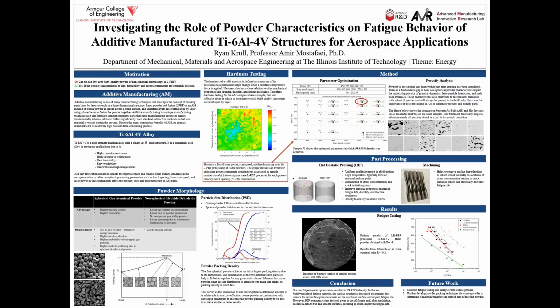To conclude this presentation, successful parameter optimization resulted in 99.935% density. In as-built plus machined fatigue samples, the surface roughness decreased, but there is still a chance for subsurface pores to remain on the machined surface and impact fatigue life. However, HIP treatment closes these isolated pores in the AM parts, and after machining results in a defect-free and smooth surface, resulting in a much improved fatigue life as seen below.